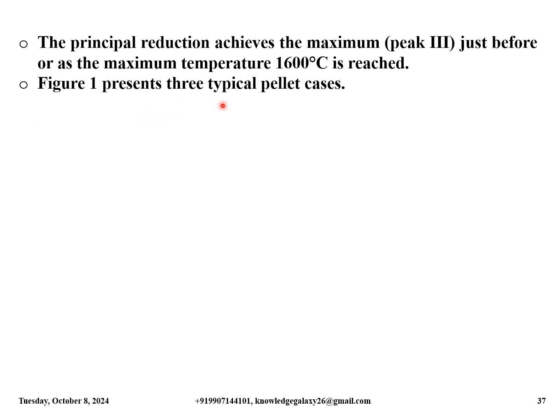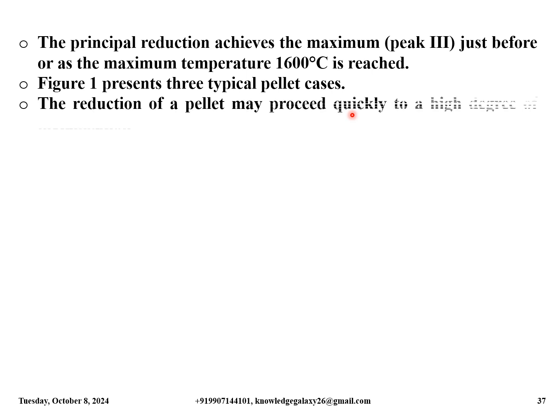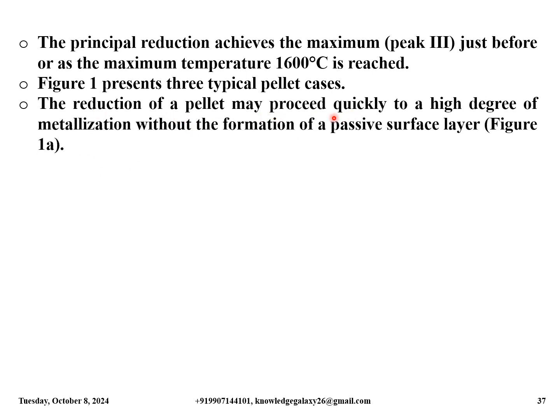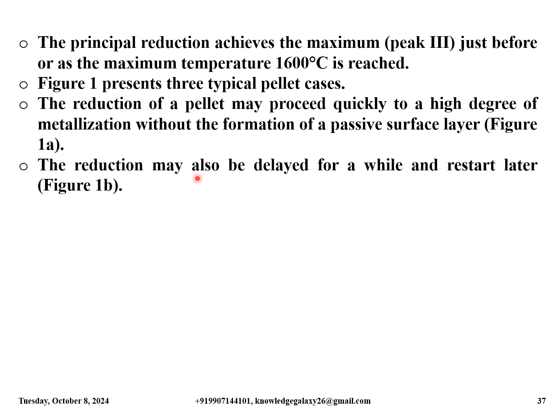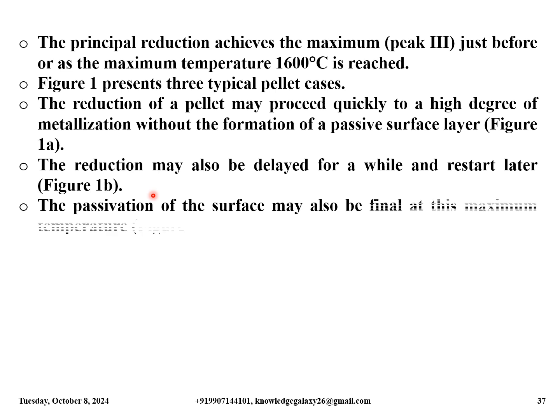Figure 1 represents 3 typical pellet cases, which are shown in the coming slides. The reduction of a pellet may proceed quickly to a high degree of metallization without the formation of a passive surface layer, as shown in Figure 1a. The reduction may also be delayed for a while and restart later, as shown in Figure 1b. The passivation of the surface may also be final at this maximum temperature, as shown in Figure 1c.